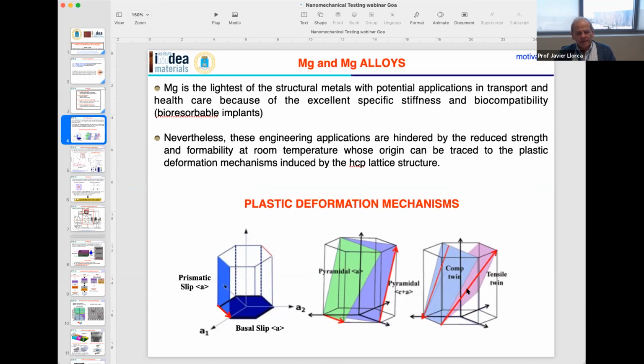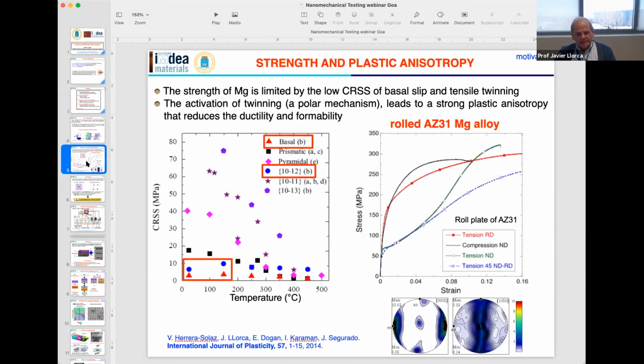And of course, you need this combination of basal slip with either pyramidal c plus a slip or twinning in order to accommodate deformation in magnesium alloys. What happens is that when you look at the critical resolved shear stress of the different slip systems in magnesium alloys as a function of temperature, you can see that there are two systems, basal slip and twinning, that have much lower values of the critical resolved shear stress. It means that at room temperature or low temperature, the dominant deformation mechanisms are always going to be the same.